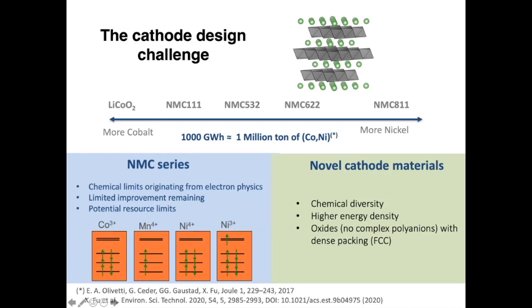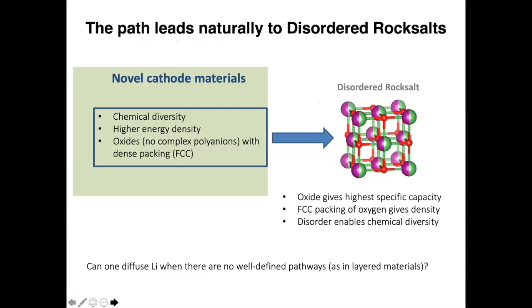And then on the anion side, it's becoming pretty clear that we need oxides. If we do polyanions, unless we can do multi-redox, the energy density will not be high enough, because we just get too much space taken up by the polyanion. And even more with the oxides, you need a dense packing of them, which is typically represented in FCC type packing. So this path leads you fairly naturally to the disordered rock salts.